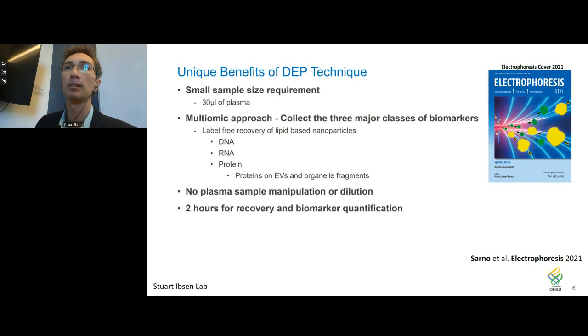What's nice about this is that it can be run in undiluted plasma, so we don't have to do any kind of sample manipulation, which really makes this a lot easier for clinical translation. The fewer steps, the easier it is for people to run this. And it only takes 2 hours for us to recover the particles and then do the biomarker quantification all on the chip itself.